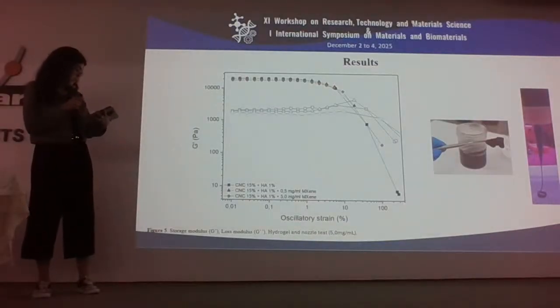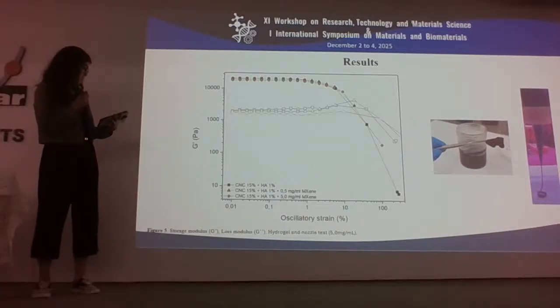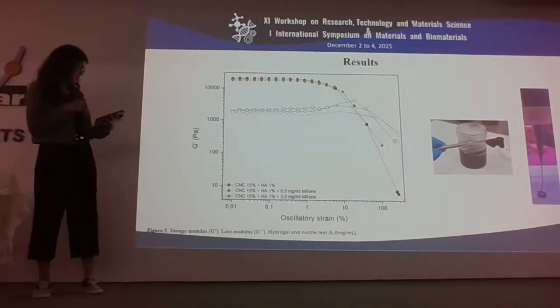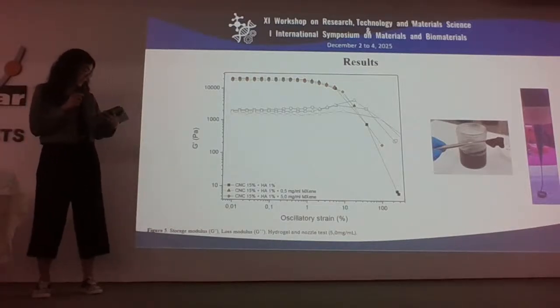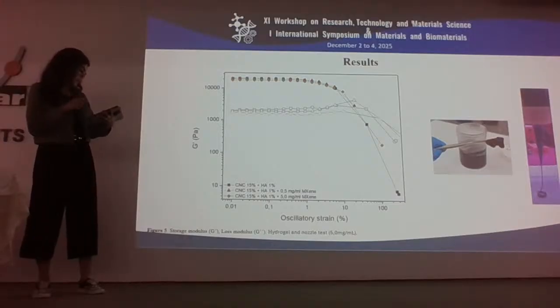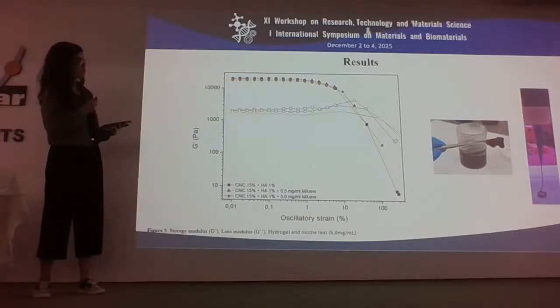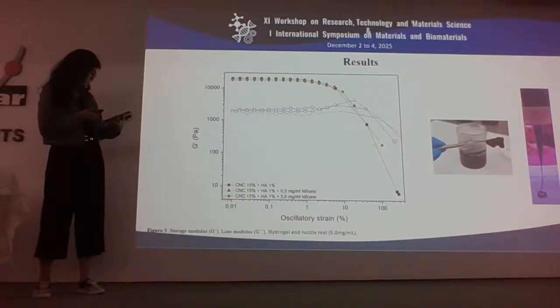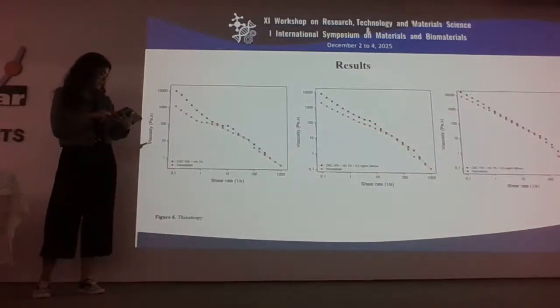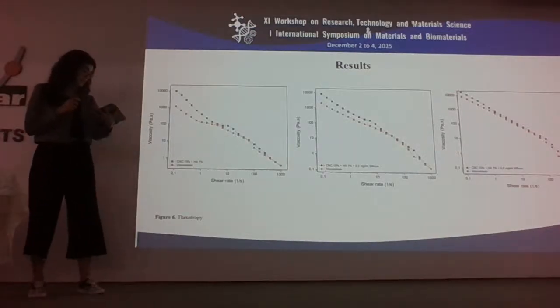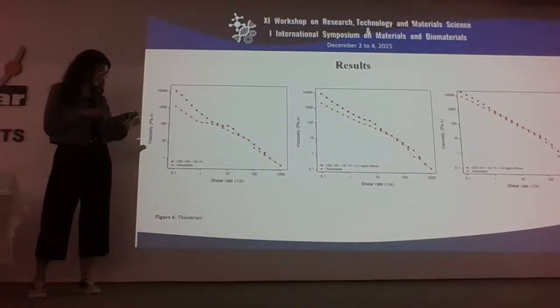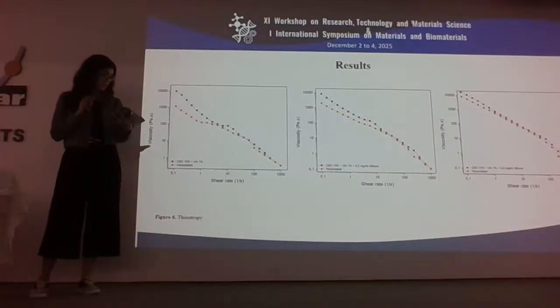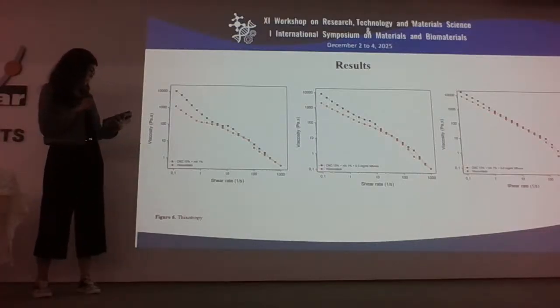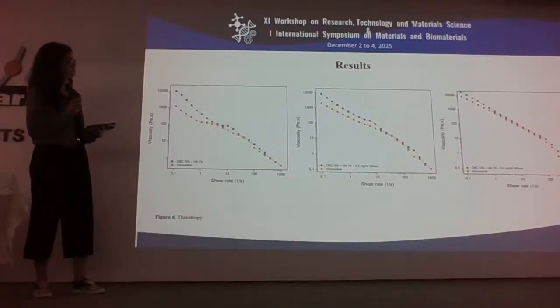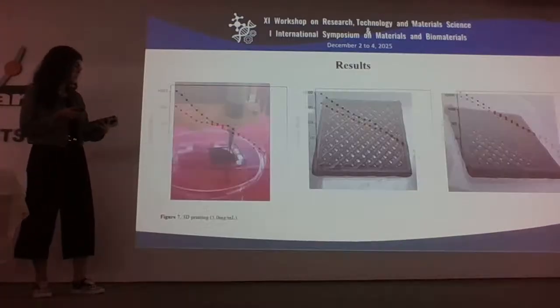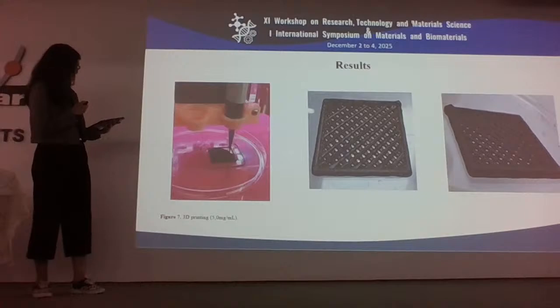The results of the storage and loss moduli showed that in all formulations there is an elastic predominance and the material behaves as a stable gel. In the thixotropic analysis, the higher MXene concentration showed a recovery level sufficient to keep the material stable during extrusion. Here are images of the prints.